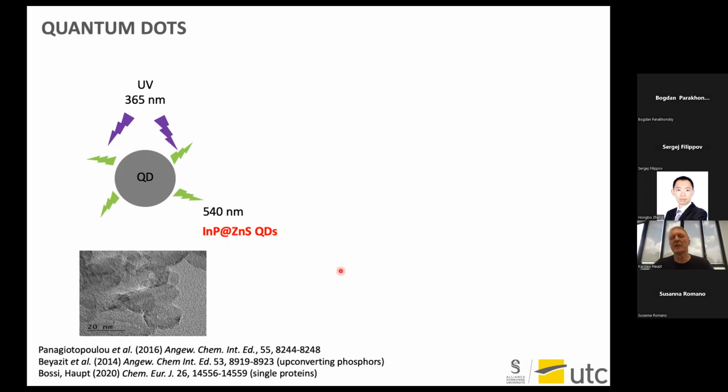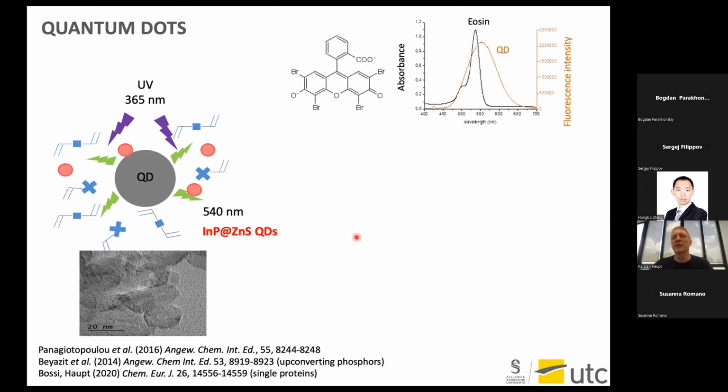So what if we use this light, the fluorescent light from the particle, in order to polymerize by photopolymerization a thin layer of molecularly imprinted polymer? For that, we have to find a photoinitiation system which is set off by this wavelength. And there are these type 2 photoinitiators that are used together with an amine that are based on a dye. Here it is eosin, and this eosin absorbs exactly the wavelength that is emitted by the quantum dot. So this is very nice.